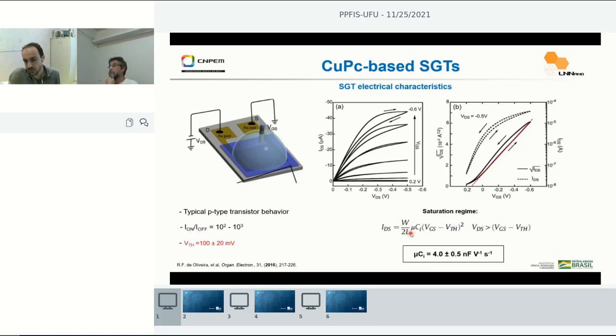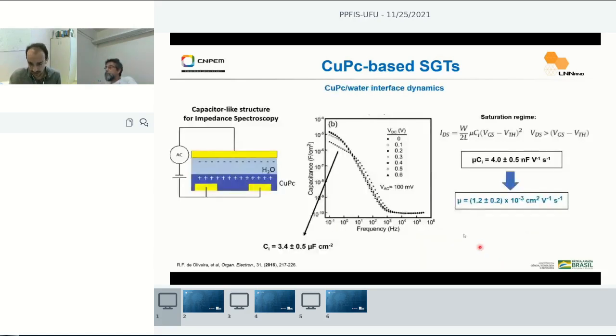And from here, what we can calculate is the product between the carrier mobility and the capacitance. So I cannot extract solely the mobility from this characterization, but I can have these two parameters multiplied together. The carrier mobility is an important parameter while characterizing semiconductor films. So these devices help us to extract these two parameters together.